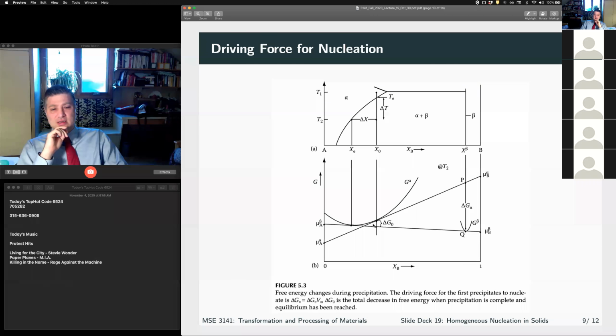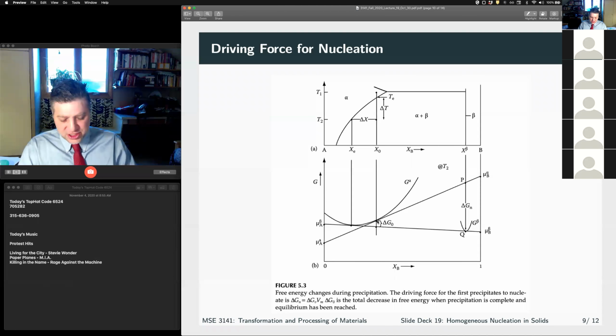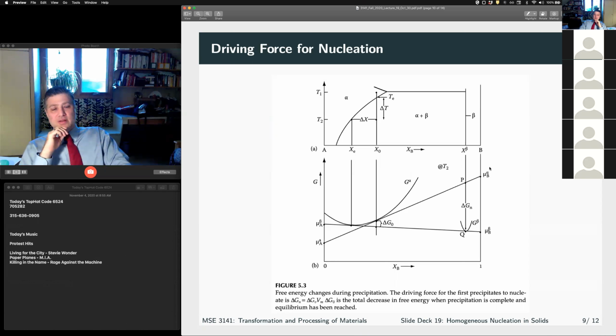The free energy of that composition, of that little block, it's still in the alpha crystal structure. I haven't actually rearranged it. So you can think of this as the free energy locally of my little cluster of size R star. It's going to be given by the chemical potential of B in alpha times the fraction of B, plus the chemical potential of A in that cluster times the composition of A. So that puts me right here at point P. So inside my little cluster, my free energy is actually way up here.